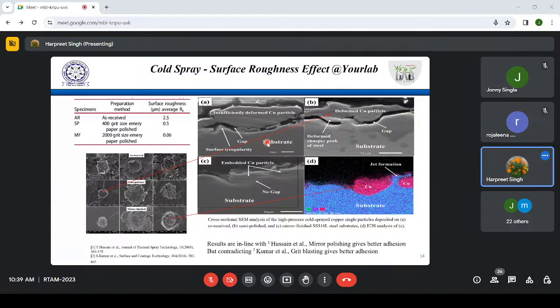When we started our experiments, the adhesion was not coming on certain rougher surfaces. But we also had mirror polished surfaces, where the adhesion was very good. So what was the reason? We understood it by single particle impact experiments. There we could see that roughness in this case was not helping, because when the surface is rough, it will have hills and valleys, right? Those peaks were getting deformed. This is the deformed copper particle. This is the deformed peak. Now this deformed peak energy is not much that it will plug this.